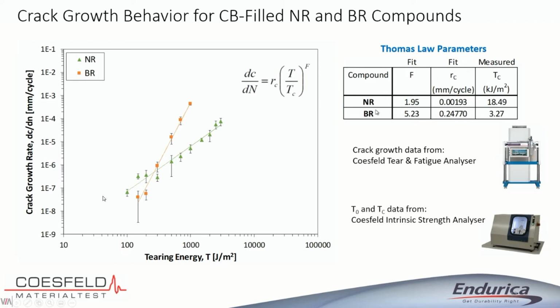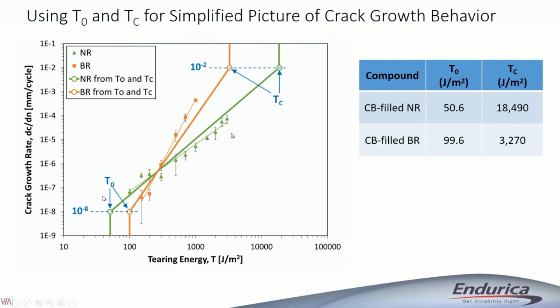But butadiene has a much steeper slope for the fatigue slope. So for natural rubber, we have about a value of 2 on F. For butadiene, we have a value of 5. And so here's what you get for the crack growth if you're running a traditional fatigue crack growth test.